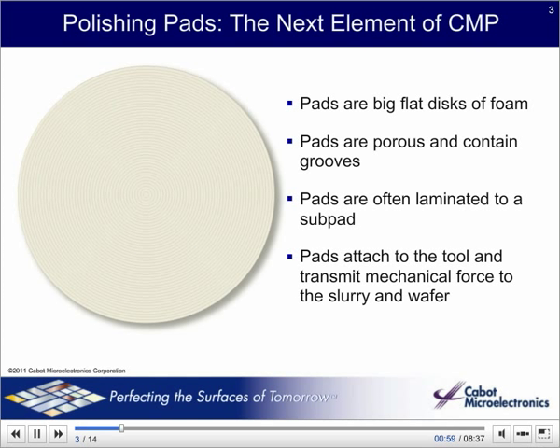Slurry is poured onto the rotating pad surface. The spinning wafer is pressed down onto the pad that has been saturated with slurry. The pad causes the rolling, sliding, and bouncing of the nanoparticles that slowly wears away the wafer surface. Chemicals fine-tune the process. Pads are quite expensive, often several $100s each, so customers want them to last a long time, hundreds or even thousands of wafer passes lasting hours or even days before they need to be replaced.